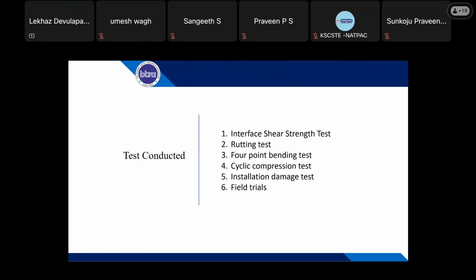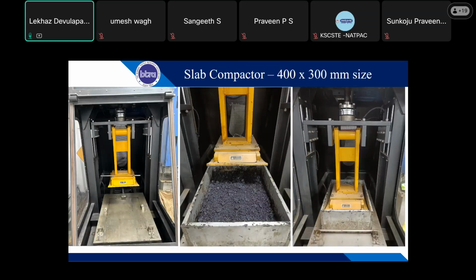Then we conducted tests like interface shear strength, the rutting test, the 4-point bending, cyclic compression, the installation damage test, and the field trials. So this is how our composite geosynthetic asphalt reinforcement has been prepared in the laboratory. This is a slab compactor where we can apply a load of 500 to 700 kPa on the specimen. You can see the mix will be prepared in an asphalt mixer, poured into a mold of 400 by 300, and compacted with the slab compactor.